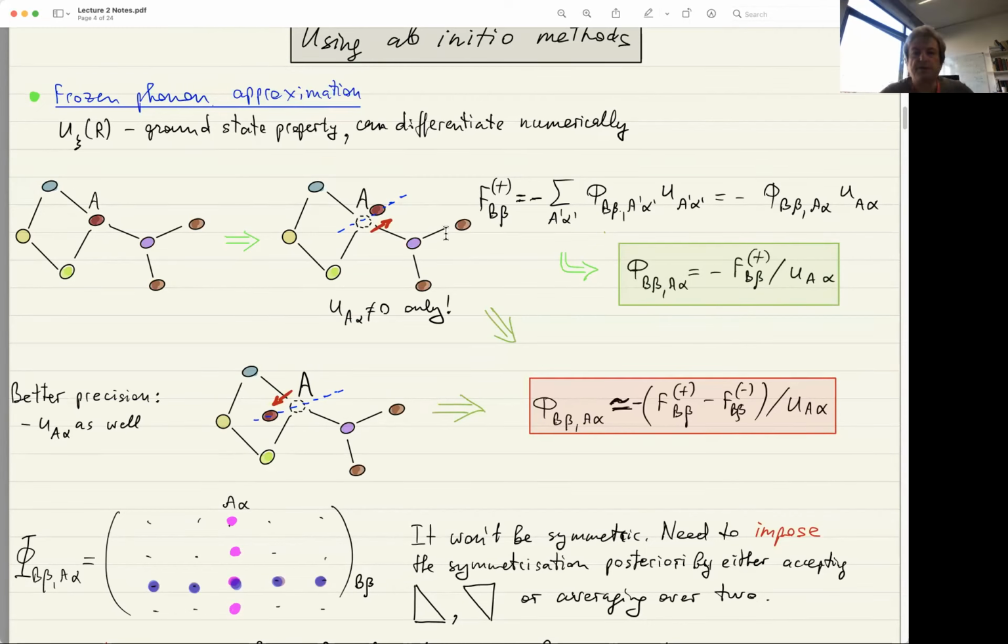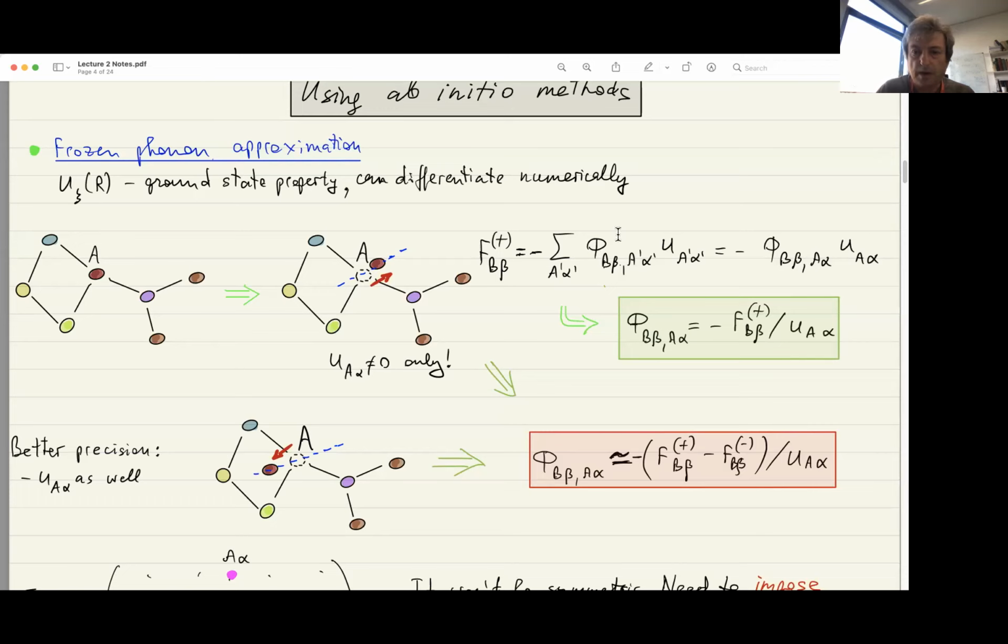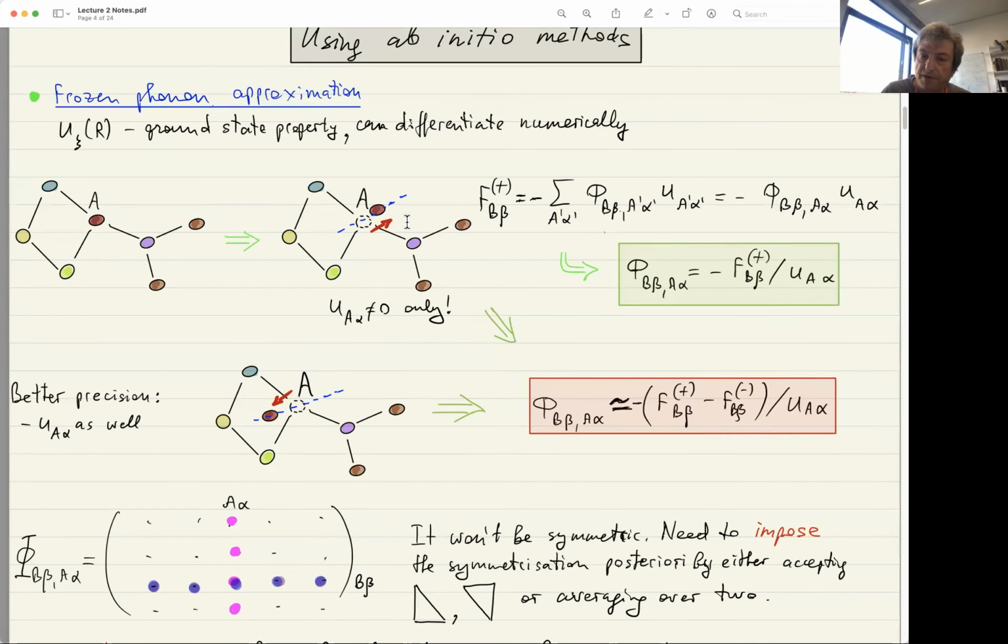All right. So this is the expression for the force. But if we displace just 1 degree of freedom, of course, of all of this sum, only one term will remain, right? Associated with the second index of that degree of freedom which we displaced. Now, if we displace this atom, we can run a calculation and calculate the forces on every atom of our system. So while we displace just 1 degree of freedom, we have the forces on all atoms of our system, including this atom. So that vector of forces is available to us.